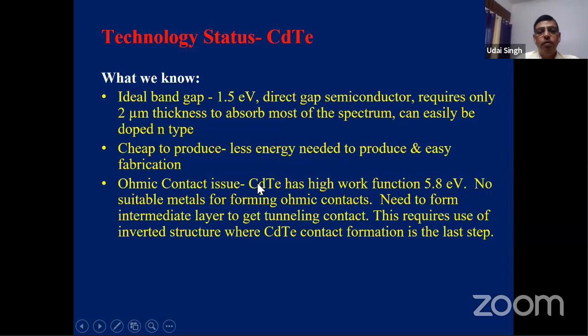The only problem with this cadmium telluride is the ohmic contact. The work function is very high, 5.8. So generally you don't find any suitable metal for forming an ohmic contact. That is the biggest problem. But still, people try certain other methods to coat the metal on this.